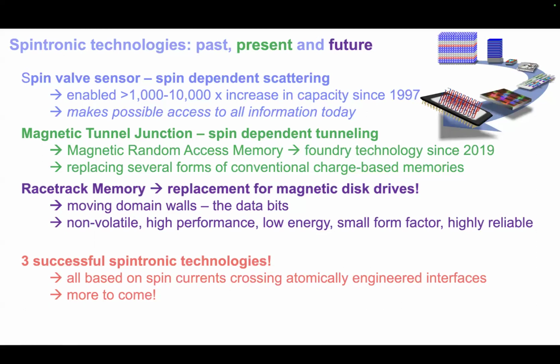We were the first to show, I don't know, six years ago, that transparency plays a critical role. If you take platinum and a nickel iron alloy, or platinum and cobalt, the transparency is twice as high for cobalt as it is for permalloy. Typically you measure spin Hall angles through these spin orbit torques, and if you don't include this transparency, you really cannot understand the magnitude of the spin Hall effect itself. So I think this is where there's very little understanding. The interfacial transparency plays a critical role, and understanding and improving on that could have major impact.